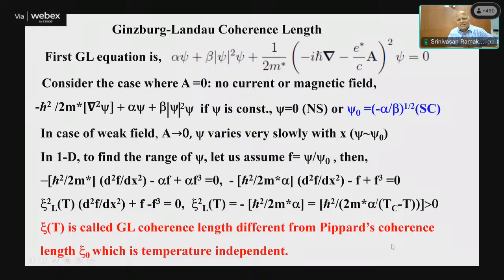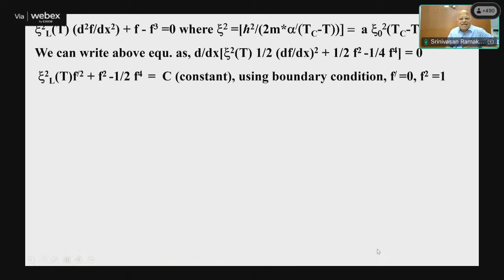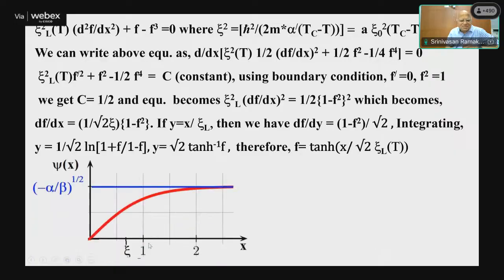So Ginzburg-Landau has an equation as a natural way to get the coherence length. And how does the wave function behave as a function of x? Then you can see that actually it goes as something like tanh of x over square root of 2 xi GL, and the wave function goes like this. And the important thing here is that for the coherence length, he was able to give an expression. That is, it goes as Tc minus T to the minus half.